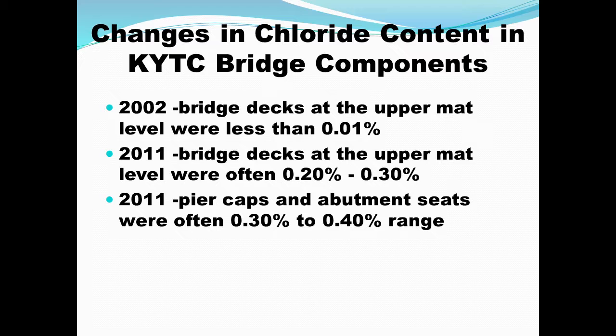In 2002, the Kentucky Transportation Cabinet sampled some 12 to 15 bridges in central Kentucky, in the Cincinnati, Ohio, Lexington, Kentucky, Louisville, Kentucky triangle, and took powder samples of the bridge decks at the upper reinforcing mat level. In none of them did they reach more than 0.01% chlorides. So they dismissed chlorides in the bridge decks as inconsequential. But in continuing to maintain those bridge decks over the succeeding 9 years, they determined that there was something going on, and they asked the Kentucky Transportation Center at University of Kentucky to go back and reassess this.